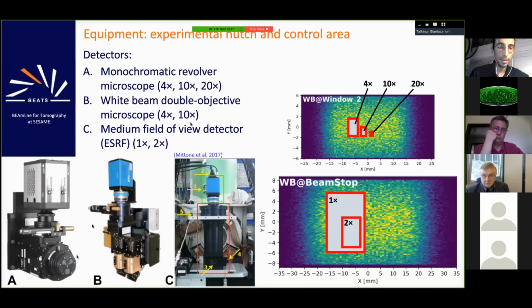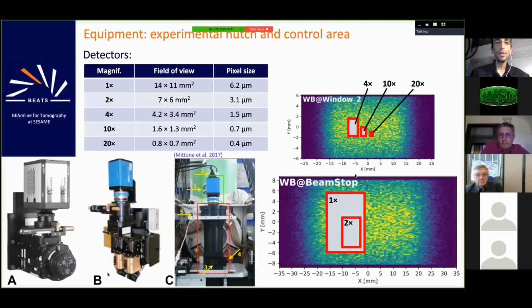And this is why the white beam microscope works vertically. The light is reflected down here by a mirror after it is emitted by a scintillator, and then the objective is placed here vertically, out of the beam propagation path, inside a lead shielding. The different detectors will give different fields of view and pixel sizes down to 0.4 microns, for a final target maximum resolution of around 1 micron.